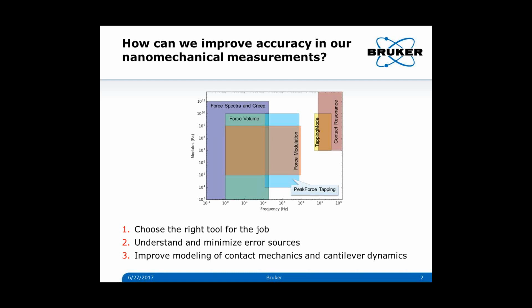We want to choose the right tool for the job, and we have a lot of options within AFM. Essentially, the AFM property measurement modes can be split up into non-resonant modes here on the left, and resonant modes here on the right. In the non-resonant modes, the Z motion is much lower in frequency, and it is not near a resonant frequency of the cantilever, whereas in the resonant modes, it is near a resonant frequency. So typically, it would be over 10 kilohertz, often hundreds or even megahertz.